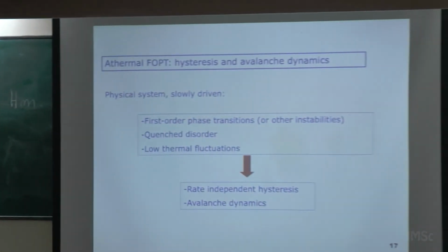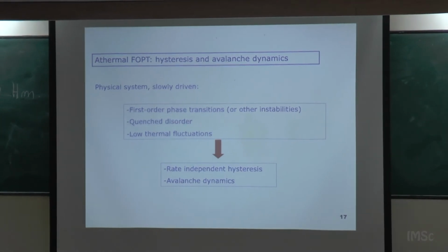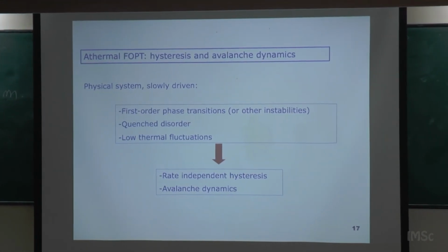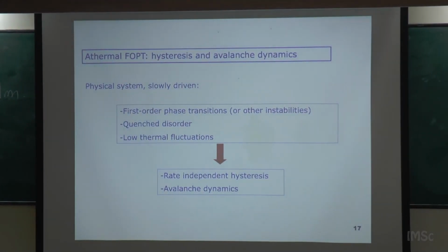In the random field Ising model, it's equivalent to say random field Ising model at 0 temperature. You write the random field, put 0 temperature, and drive with the field. The system will exhibit avalanches and a power law distribution of avalanches. Sure. So athermal is the tricky thing. Effectively, it's as if you were at 0 temperature. But it's not the ground state, because the ground state is the absolute minimum. It's a local minimum.